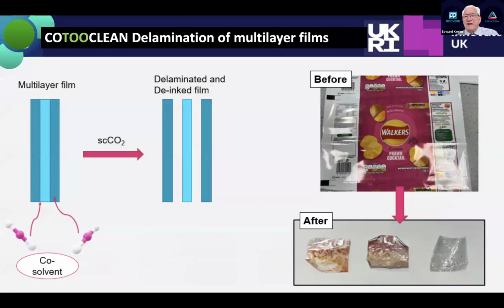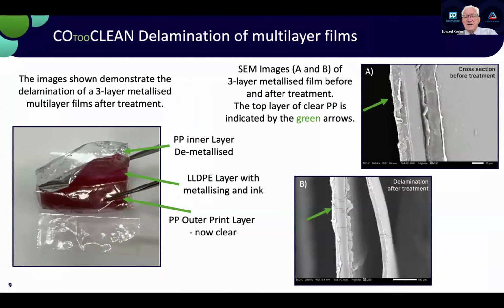So just to say a few words about metallized materials, we found in our process we can actually penetrate the layers and create delamination between the layers. So this is a crisp packet, which you can see what the film looks like beforehand and also what it looks like after the process. So we can actually delaminate the layers. In this case, we end up with 2 PP layers on the outside and a linear low density layer on the inside. And this is quite a simple and also quite a powerful process for demetallizing. And in this slide, you can see the SEM images of the delaminated materials. So a very interesting and very important technology to have.